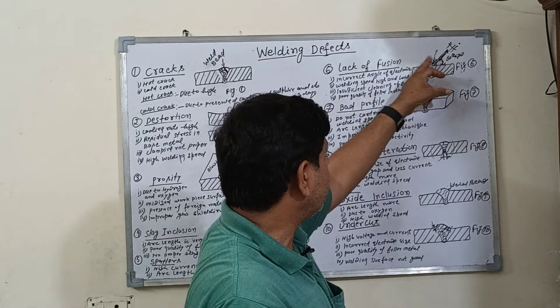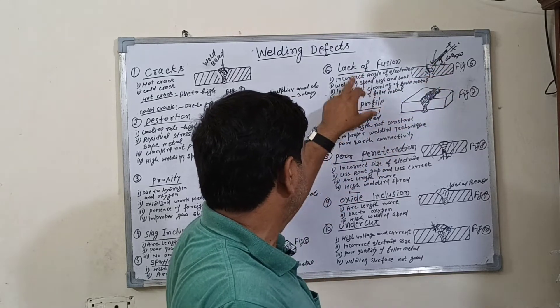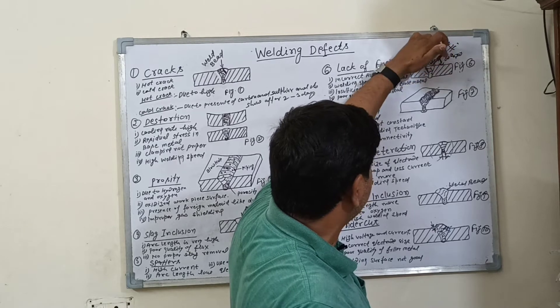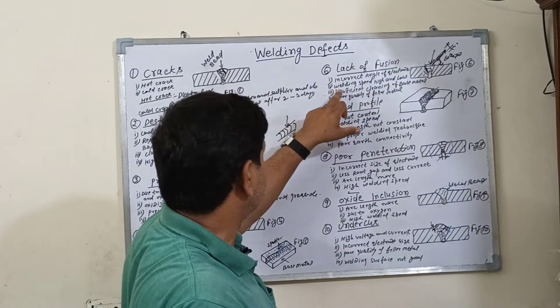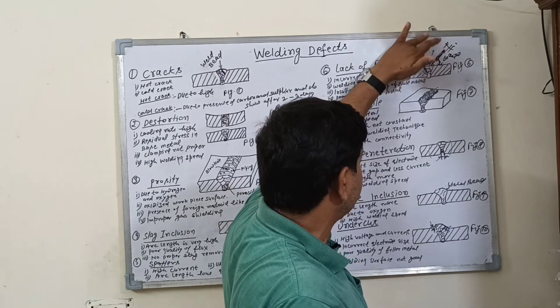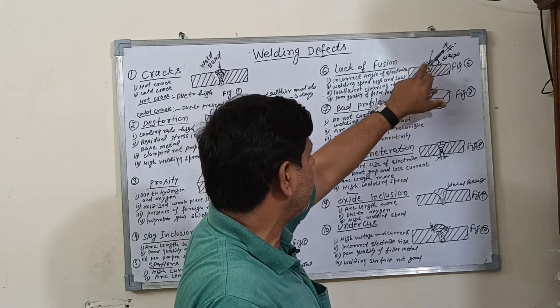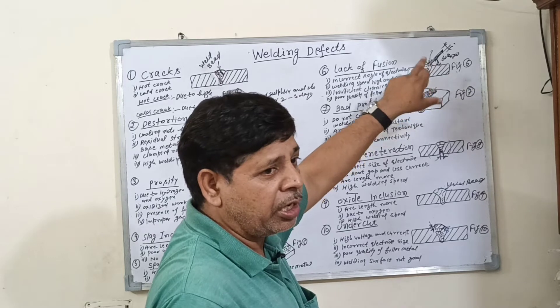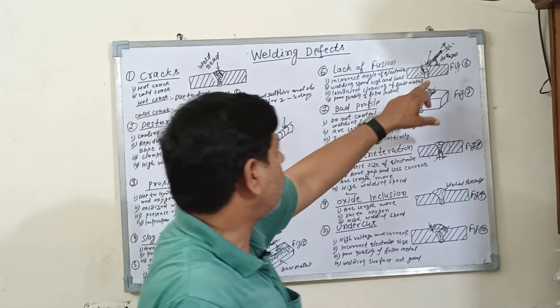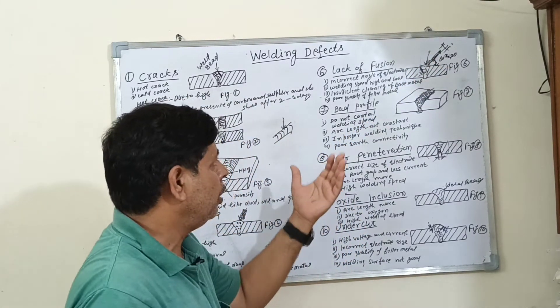Number six is lack of fusion. Lack of fusion means the metal is not properly melted. The reasons behind it include incorrect angle of the electrode position — the electrode from the surface should be inclined at 60 to 70 degrees. Other reasons are welding speed being too high or too low so the metal is not properly fused, insufficient cleaning of the base metal so the area should be neat and clean with no dust or rust, and poor quality of the filler metal.